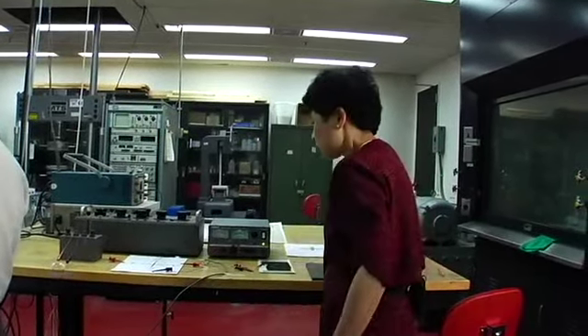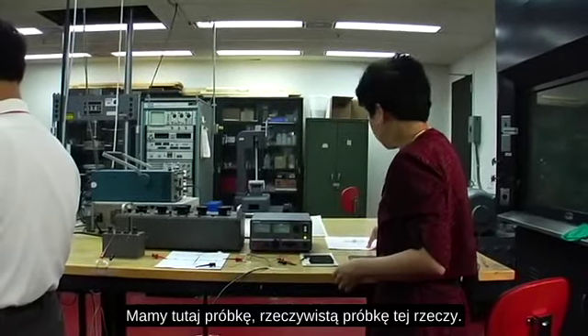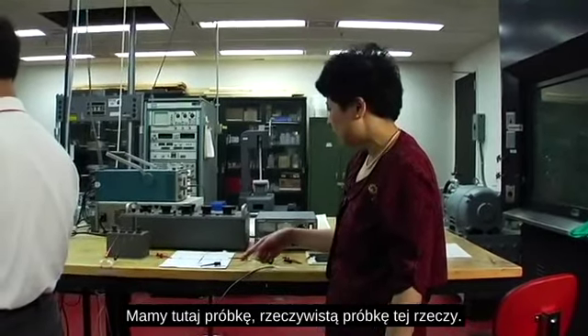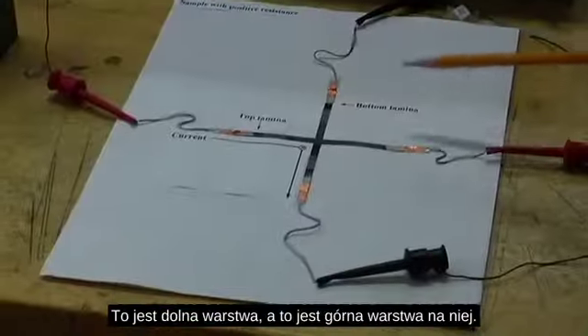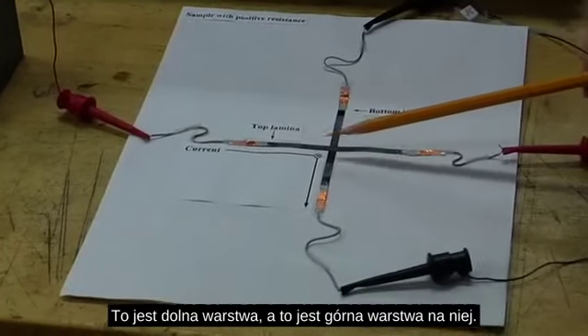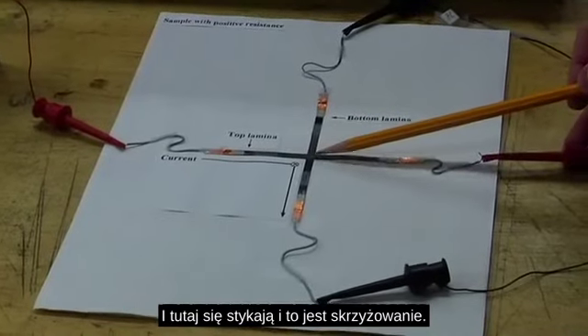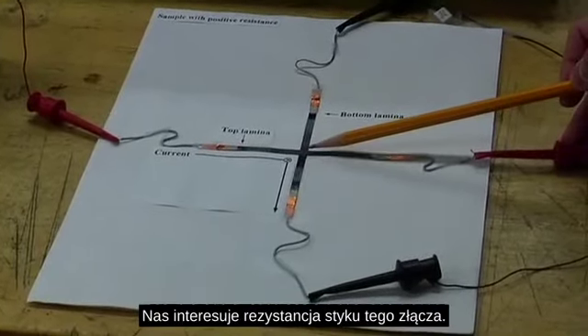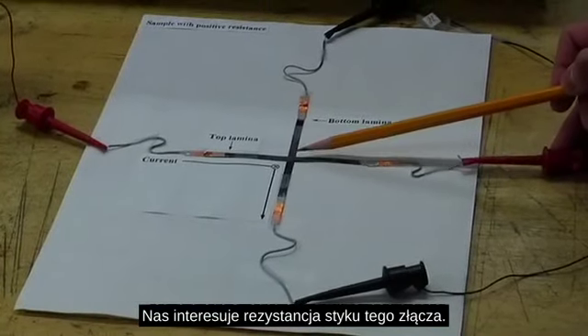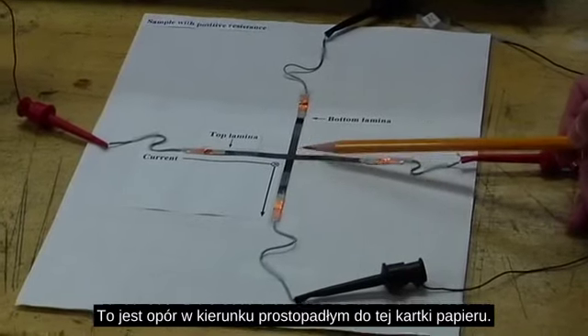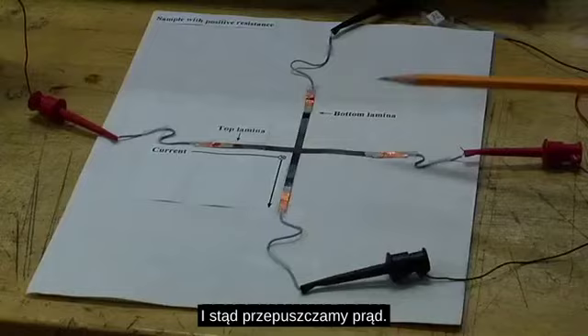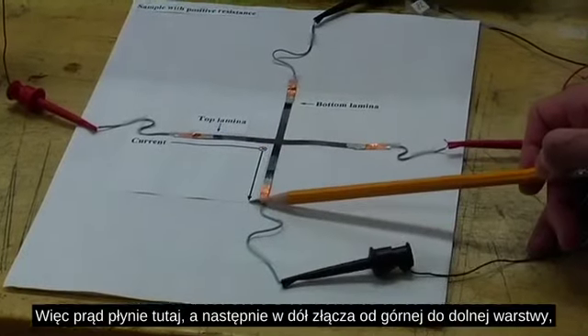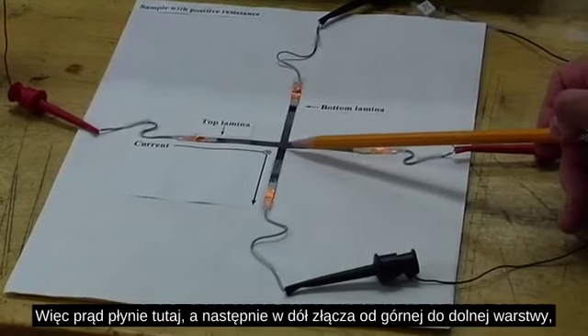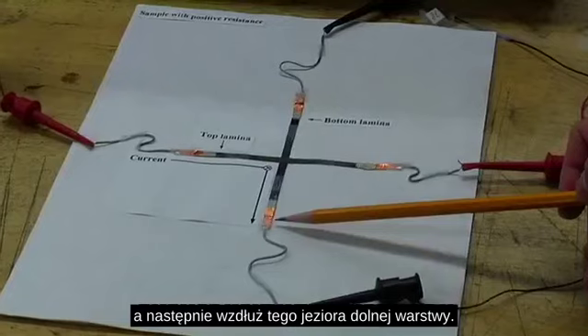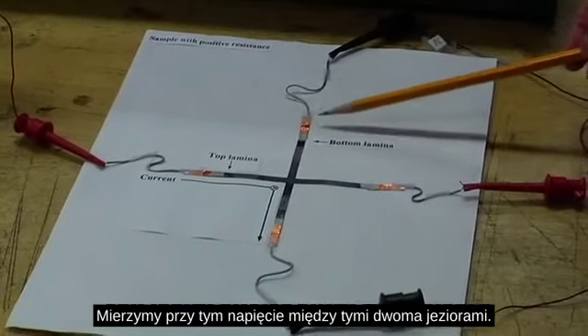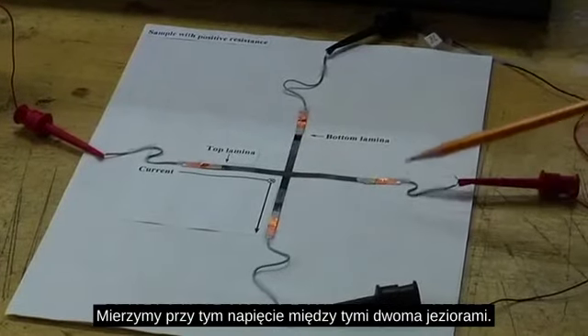Okay. So we have here an actual sample of that thing. This is the bottom lamina, and this is the top lamina on top of it, and this is where they touch, and this is the junction. And we are interested in the contact resistance of this junction. That is the resistance in the direction perpendicular to this piece of paper. And we pass current from here to here, so that the current goes here and then down the junction from the top to the bottom layer, and then along this leg of the bottom layer. And while doing that, we measure the voltage between these two legs.